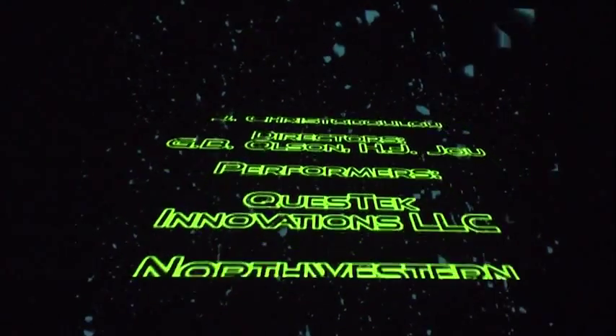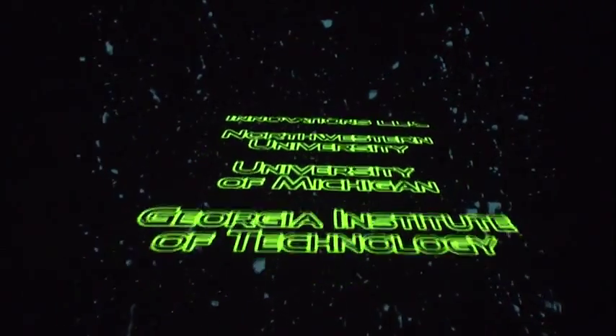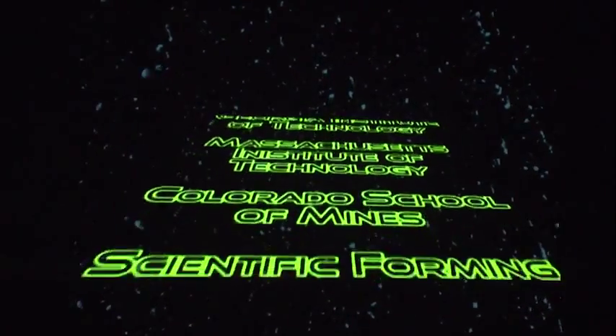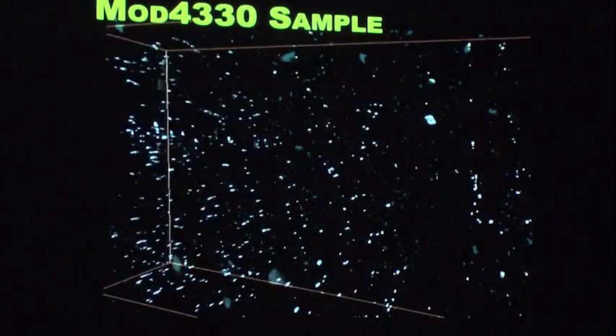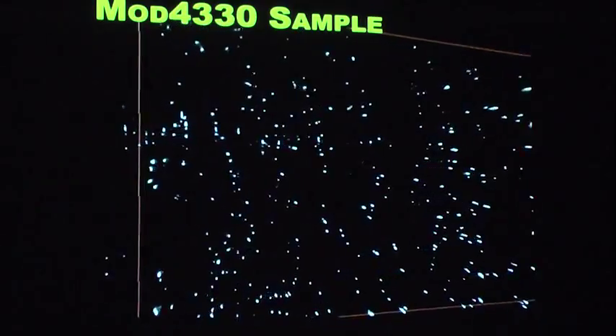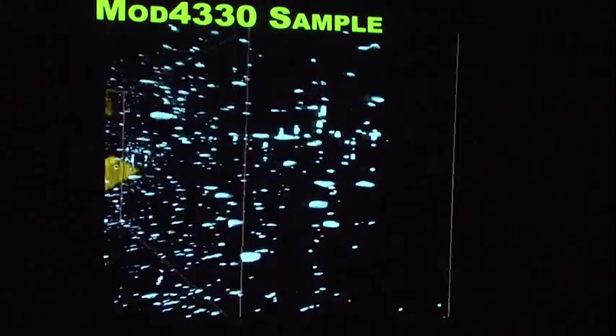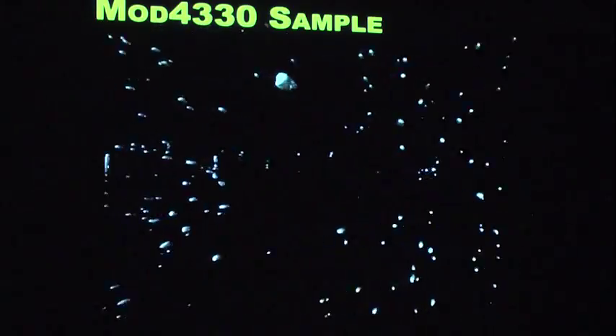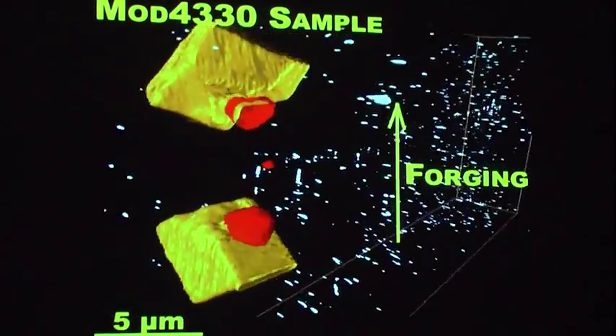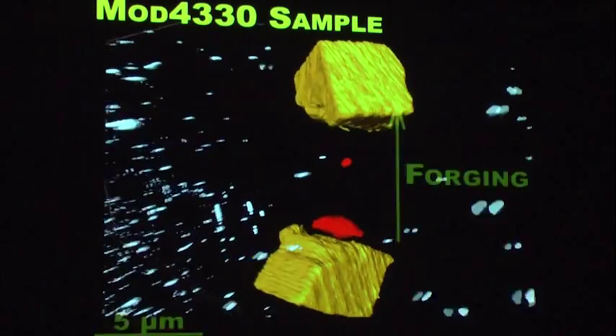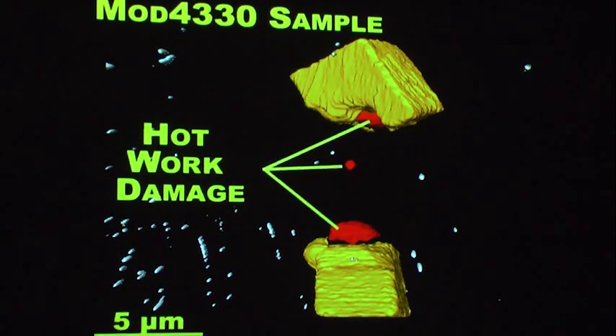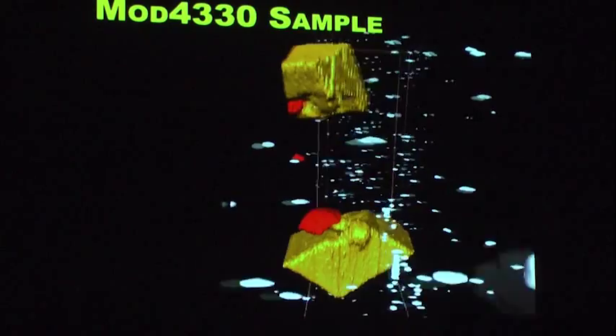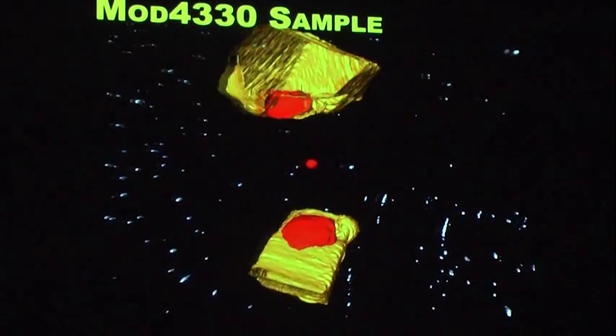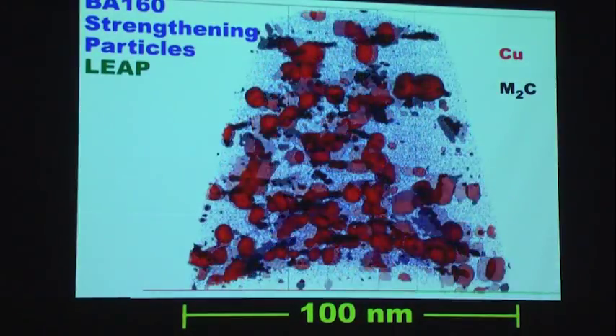The space you are flying through is the submicron titanium carbide grain refining dispersion in a 4330 modified martensitic steel. And that's shown with a little better resolution. This is from FIB-SEM reconstruction, where the white particles are the titanium carbides. Also shown are the primary titanium nitride inclusions, and very importantly, the interfacial damage inherited from prior deformation processing. Our micromechanical fatigue simulations show that this is a particularly important attribute in the nucleation potency for fatigue.